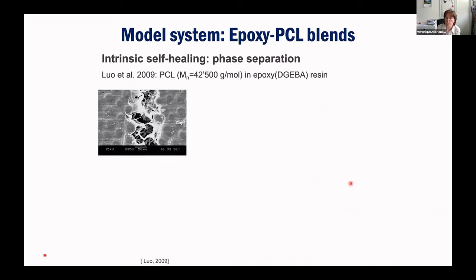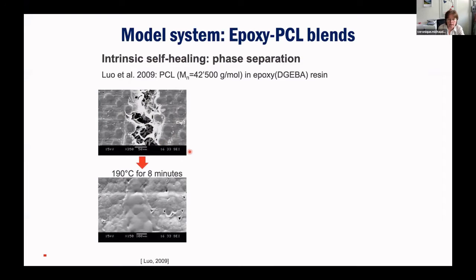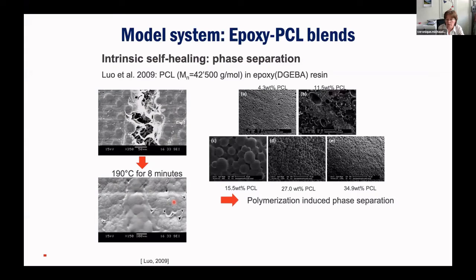So we started by working a lot on the model system, which is epoxy with polycaprolactone blends. We found in the literature that this was done before, and that was our inspiration, that, for example, in mixtures of epoxy and PCL, we could see from the literature that there is an interesting microstructure, and if you have a crack, in that case, they heated it at 190 for 8 minutes, and you see that the thermoplastic has filled the crack.